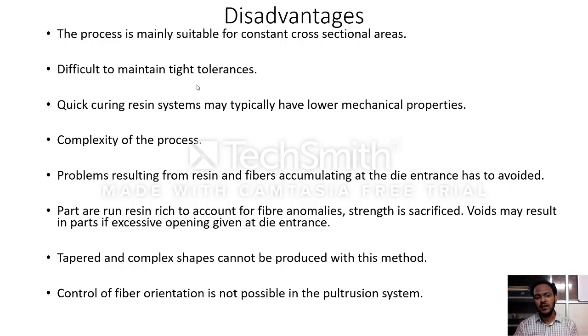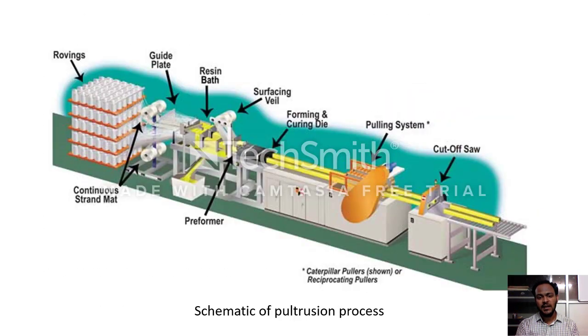As you have seen in the figure, you can see this is the place where the forming and curing take place. So it is a very small portion. At this place only the curing and forming take place. So the curing process takes less time to cure. So if you want to do a quick curing, in that case you have to make some compromise when it comes to the mechanical properties. You may not get the good mechanical properties when you do the quick curing.